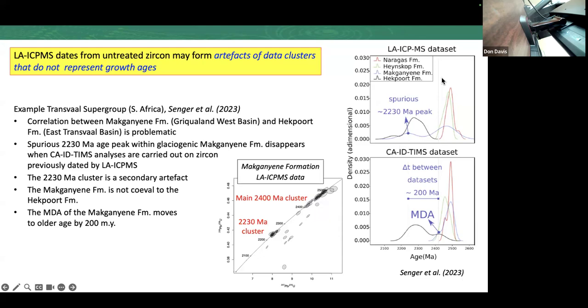But in any case, I think personally only a fool would try to use LA-ICPMS to date Phanerozoic rocks because it's so difficult and potentially inaccurate. But my experience in Archean and Proterozoic rocks is that it's really, really useful because you can use almost any zircon, basically. The trouble with ID-TIMS is that you have to go through the whole population of thousands of grains very carefully and pick out what you think are the best grains, which are highly unrepresentative, or could be, of the main population, of course. Whereas even if you have a grain that's totally cracked up, as long as you have, you know, a 20 micron size domain within there which is not damaged, then you can apply LA-ICPMS.